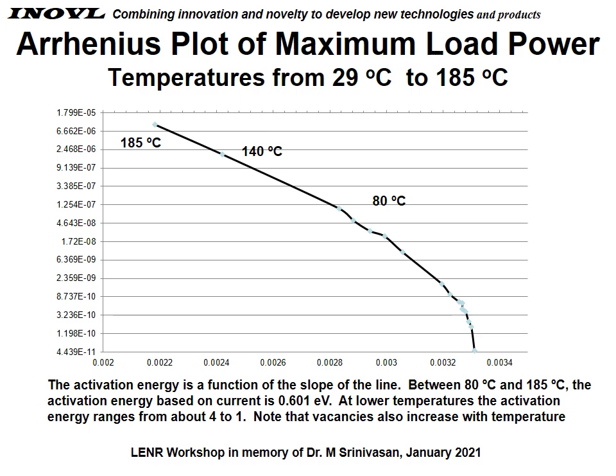Here's an Arrhenius plot of the maximum load power at temperatures from 29 degrees C to 185 degrees C, versus the inverse temperature. You can see in the far right, which is about room temperature, that the slope of the line is pretty steep, and it gradually bends over until, by the time it's 80 degrees C to 185 degrees C, we get a very nice straight line.